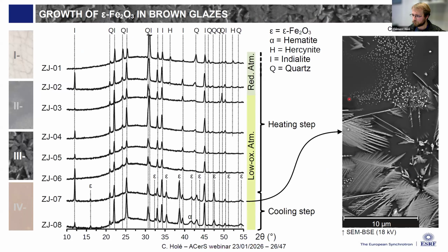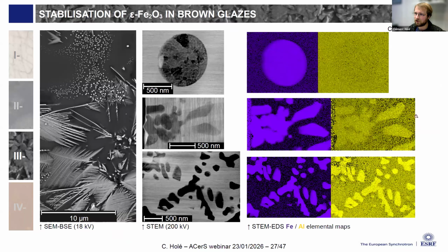To go a bit further about this growth mechanism, I focused particularly on sample 7 because it was extracted from the kiln at a quite high temperature, and it displays a very interesting microstructure on the surface. So you can see these tiny white dots here are identified as iron epsilon oxide. They have this very characteristic Raman spectrum. Then we have the very big dendrites that we can find in archaeological samples. And they also have these intermediate structures with both the dots from which the big dendrites are growing, showing that indeed we could have some iron concentration with very, very small crystals at the surface. And from this spot, some crystallites would have better orientation and better growth chains, and they would completely grow to fully fledged dendrites.